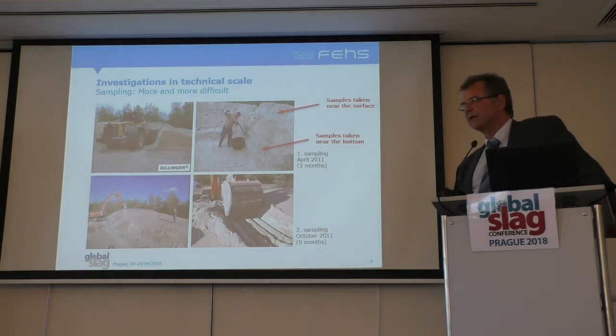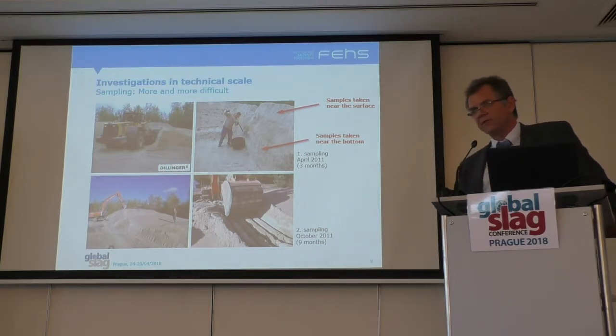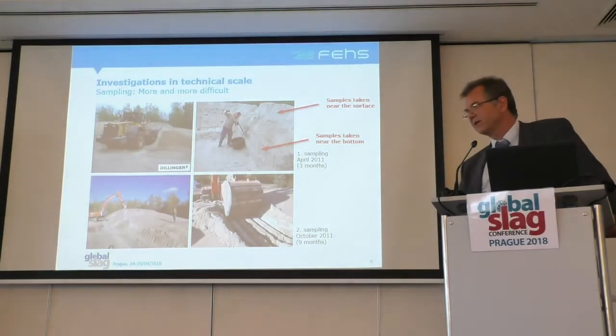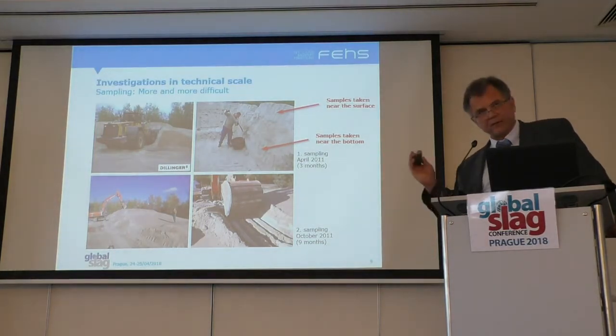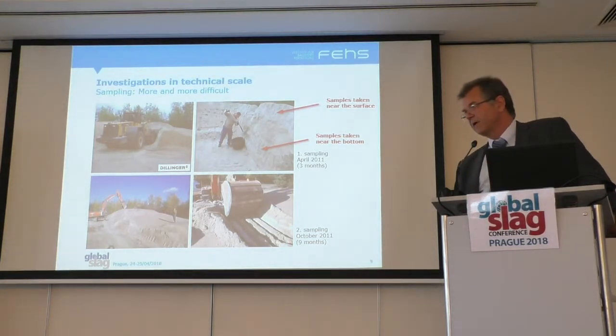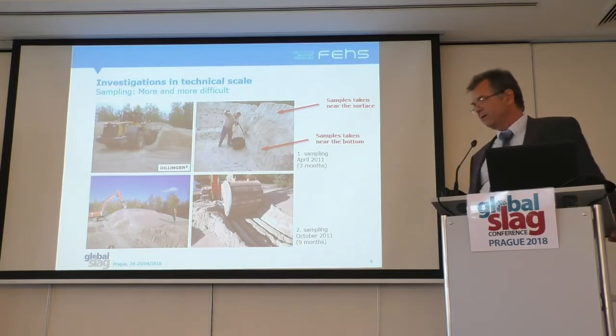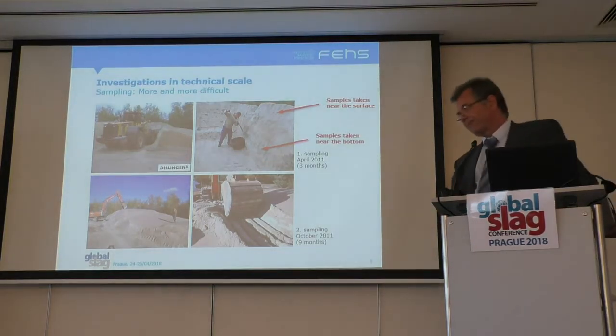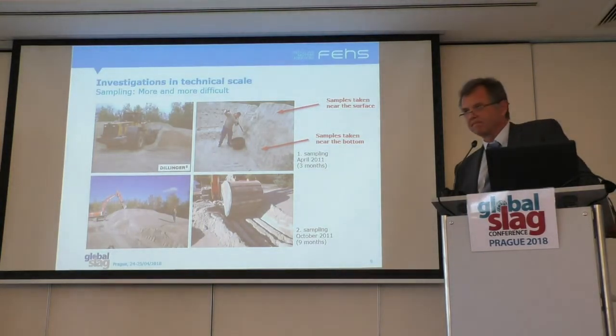All results consider only the samples taken from the bottom, because in the outer part you have indeed drying, in summertime, sometimes it's raining and so on, so the chemical effect, the prehydration effect, is much lower. Therefore we look to the main part, let me say, of the slag, which we took from the bottom. Right. Worst case, let me say. Yeah, I'll give you that.